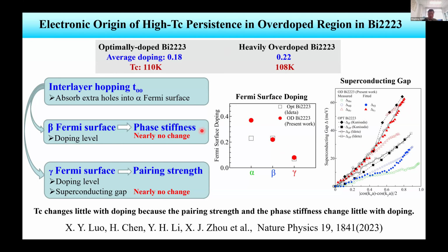As we know from the composite picture, the gamma Fermi surface is responsible for the pairing strength, and the beta Fermi surface is responsible for the coherence. But these two Fermi surface sheets do not change much with doping, and that's why TC does not change much in the overdoped sample. So by using the composite picture, we can understand why TC does not change much in the overdoped sample. This is basically the work we have done on the Bi2223 sample.